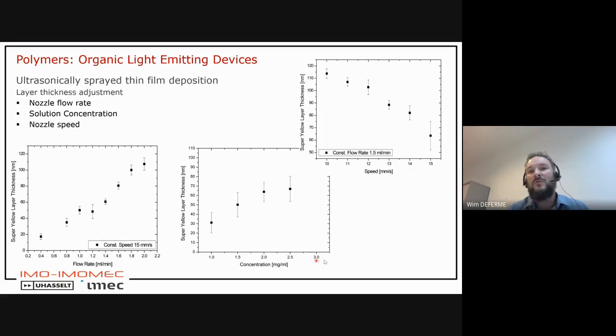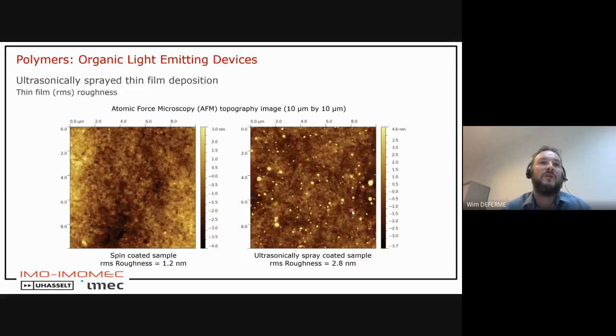So we need to go to a concentration of 3 to 4 milligrams per milliliter to achieve around this 80 nanometers. But we saw that going higher than this, 4 milligrams per milliliter, gives us some problems in ultrasonic vibration, in efficiently transferring the power into a specific wavelength or amplitude to generate a droplet. So that's something that we took into account.